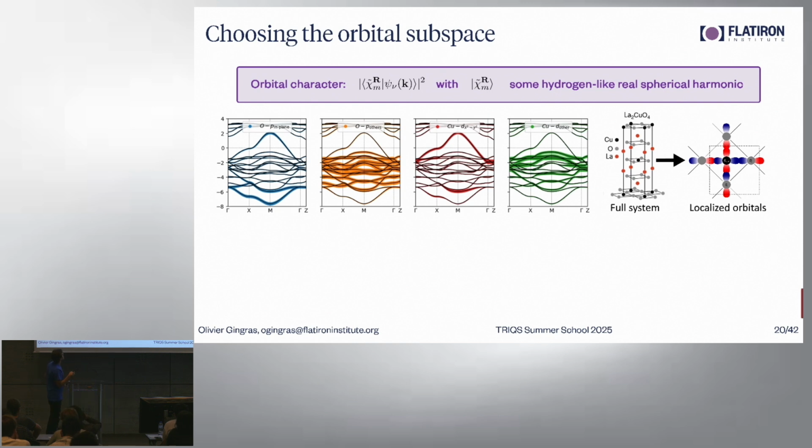Okay. The other interesting atom here is the oxygens. There's 4 oxygen in this material. So knowingly, I decided to plot the in-plane orbitals. It's not exactly in plane, it's really these 2 orbitals, actually. So if I plot the orbital character of these 2, I find this kind of orbital character. Again, there's a lot of overlap at the Fermi level. And if I plot all the other orbital characters of the oxygen, this is what I find with almost nothing at the Fermi level.